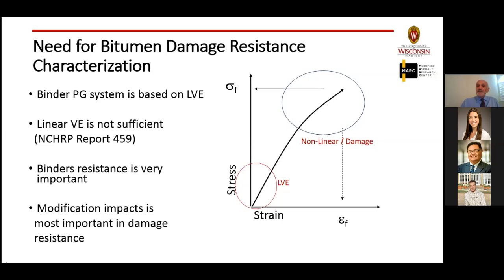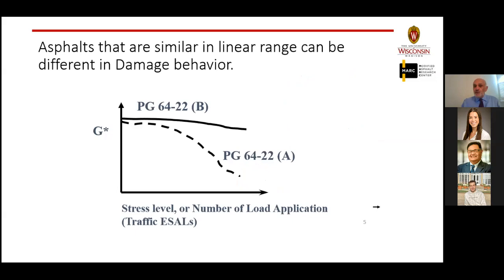We also found in field or lab studies that the modification impact is actually most important in the damage resistance, not necessarily only in the linear viscoelastic range. There is some effect of the modifiers. We change the PG grade by putting in additives and so on. But if you look at the total behavior, particularly in damage, you see most of the benefits of these more expensive materials appear in the damage. Here's an example of what you find. Now, this is a schematic, but I'll show you actual data.